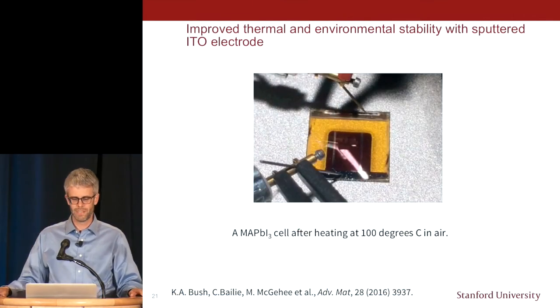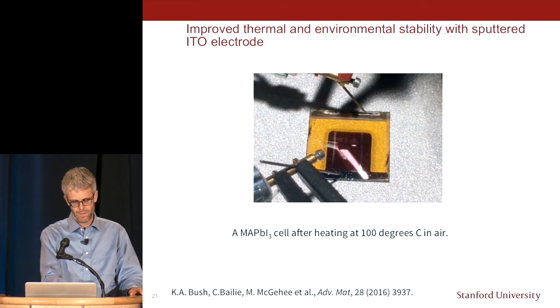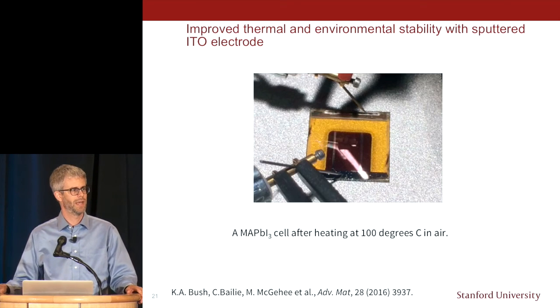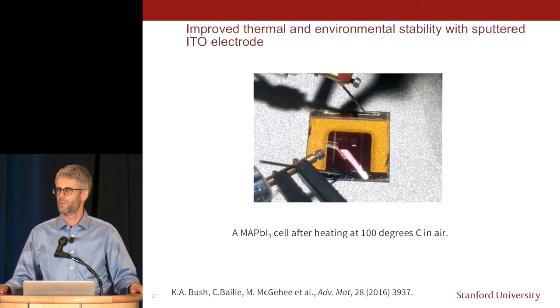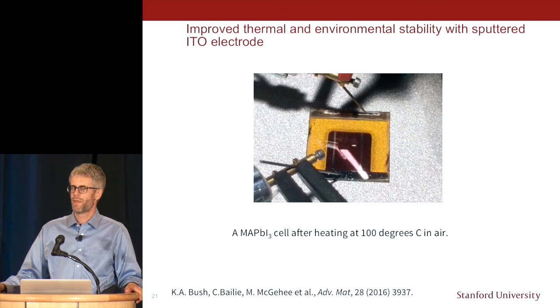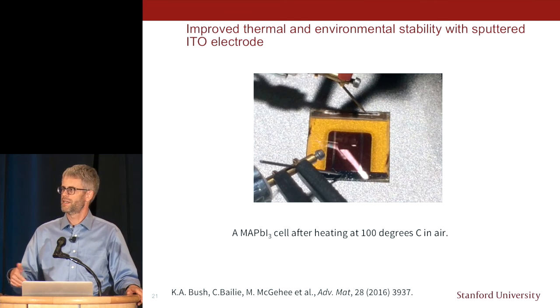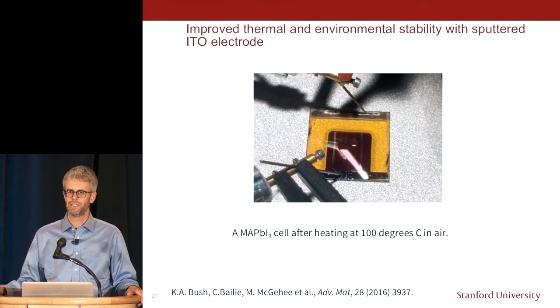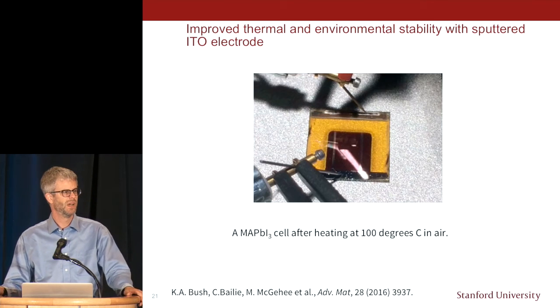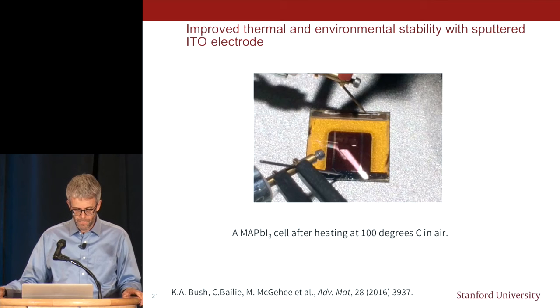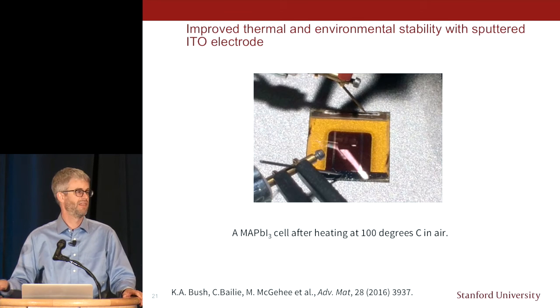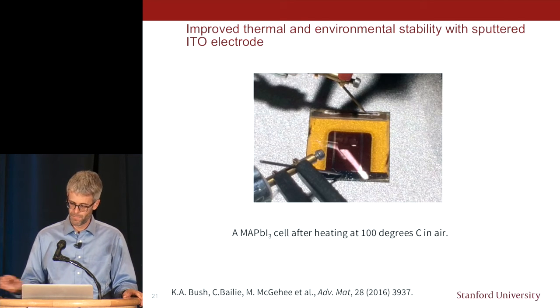So here's a picture of a cell that's been on a hot plate at 100 degrees. The reddish square, that's where we have ITO. Yellow is where we don't have ITO. When methyl ammonium leaves, you're left with lead iodide, and the lead iodide is yellow. So you see that the ITO holds in the methyl ammonium, and you get a 10,000x improvement right there.